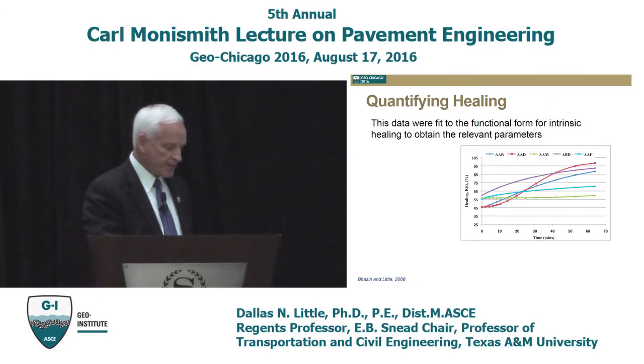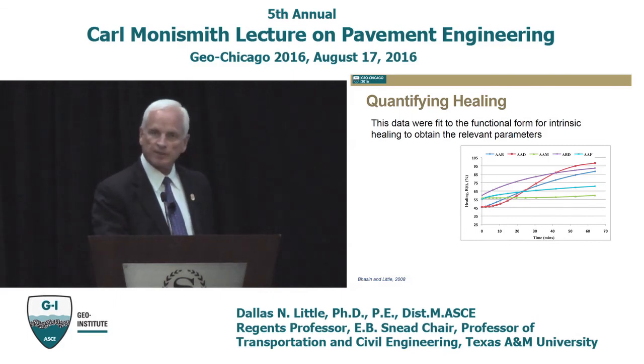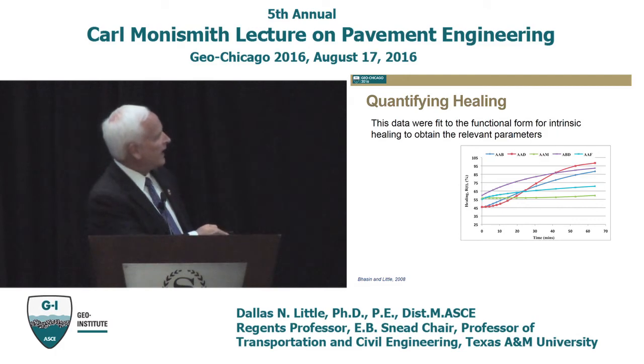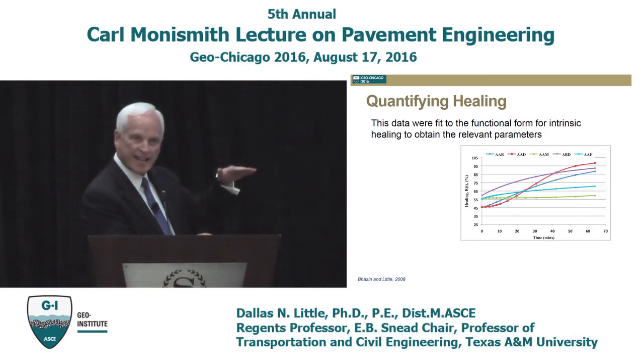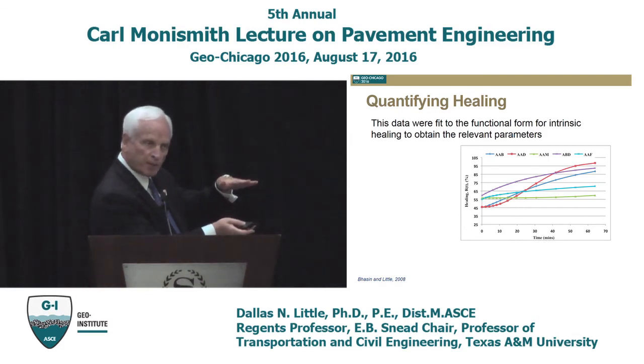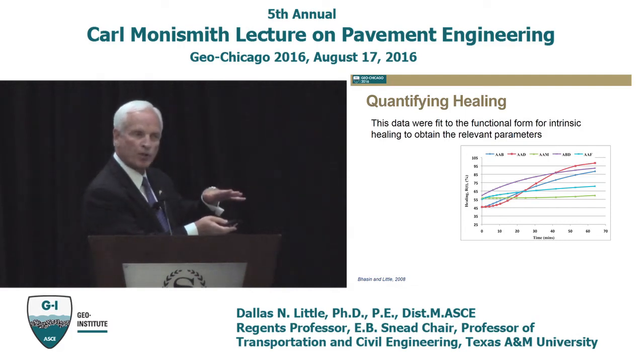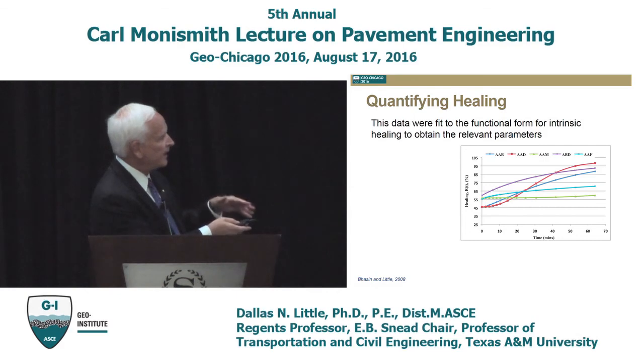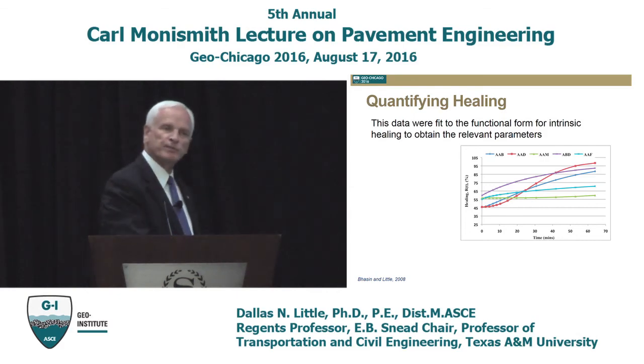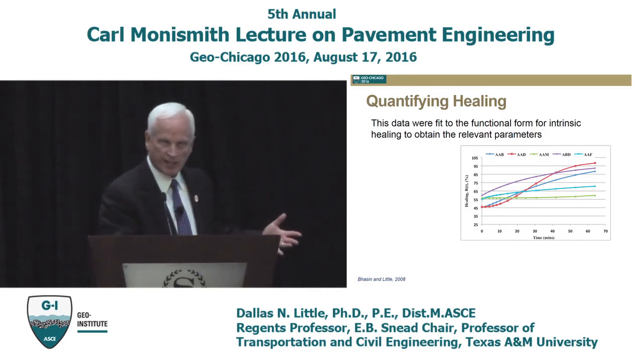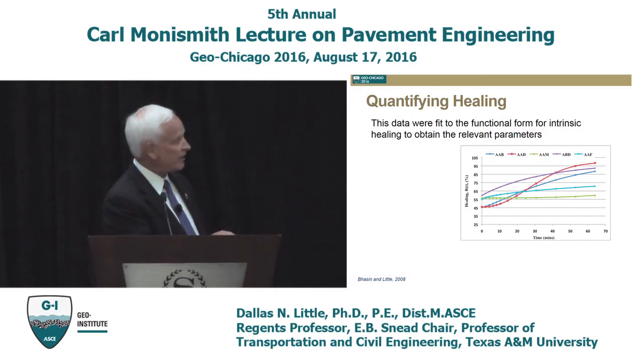So we looked at a number of asphalts in some of our early studies in healing with Amit Bhasin. And here is the response to healing. This is the percentage of healing. If you take an asphalt, you separate the asphalt and you allow it to come back together through a very nominal compressive force, and you allow it to heal. You measure the healing. I won't go into that. I don't have time on exactly how you do it.